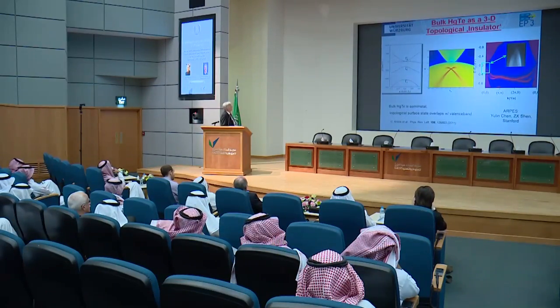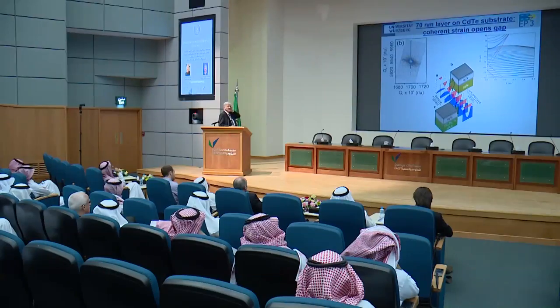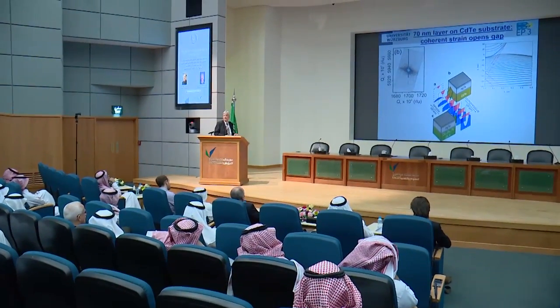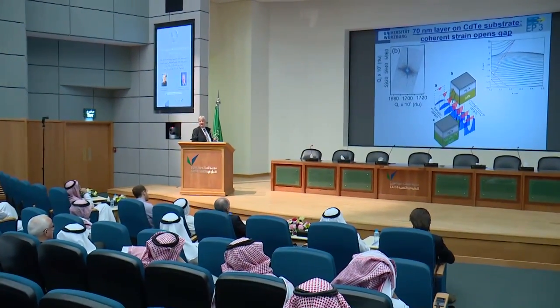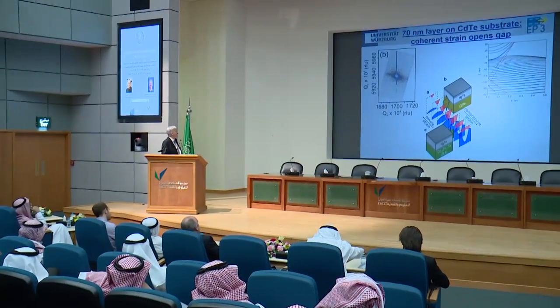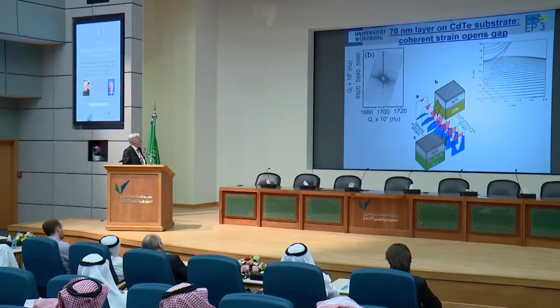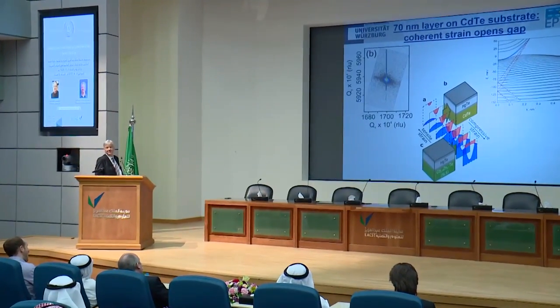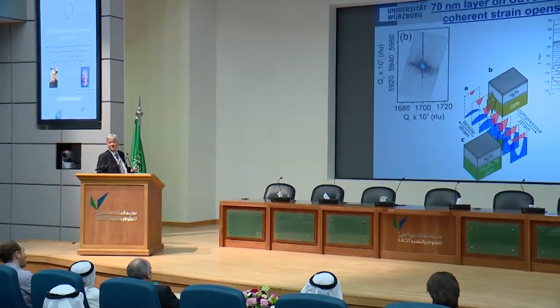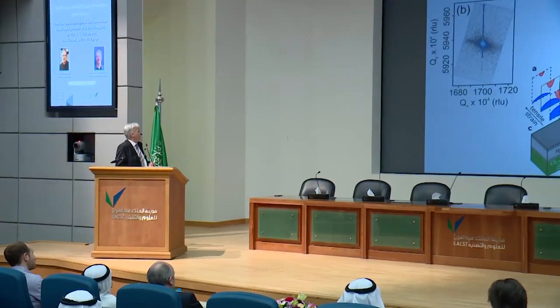What you can do actually now is play with your band structure. And we do so by straining our layers. This is called band structure engineering. And well, one easy thing to do is actually grow on cadmium telluride substrates because the lattice constant is 0.4% larger than that of mercury telluride. Now, if you have this tensile strain, basically what you see here is you open up a gap. You simply pull these two gamma 8 bands apart. And this is just to show that we can grow these layers in a strained fashion.